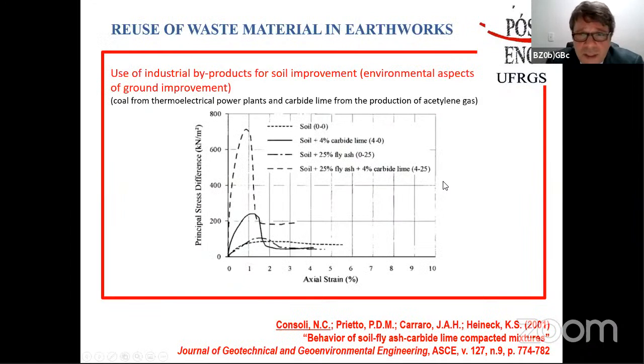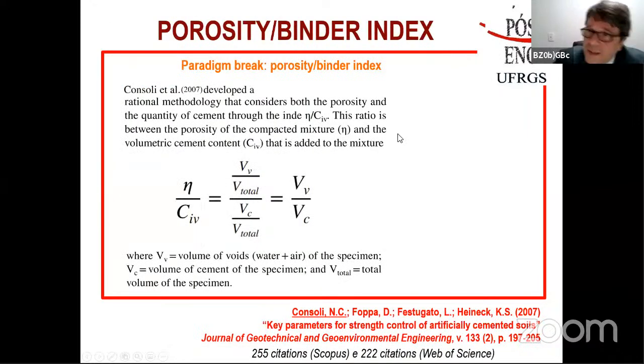Here, just to show a quite ancient result from 2001, when we published the behavior of soil mixed with coal fly ash and carbide lime, so both residues. And we can see here, if you just have the soil, if you have soil with 4% of carbide lime, you have something stiffer, but if you put some fly ash and the carbide lime, then you have a very good situation in which the pozzolanic reactions are excelled in this case, and you can get quite nice results.